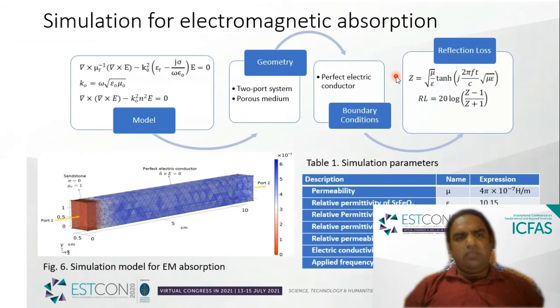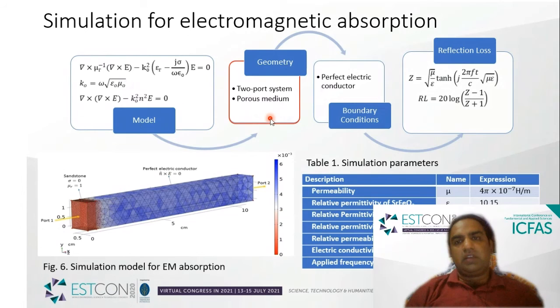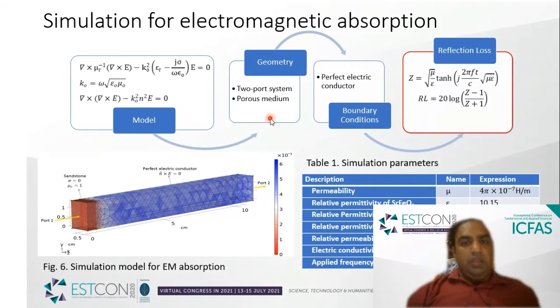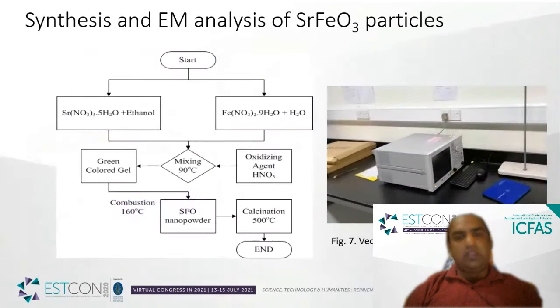So in the working part, we did some simulation for electromagnetic absorption, in which we proposed the model, and then we had some geometry in which a two-port porous system was used. We set the boundary conditions, which were the perfect electric conductor, and at the end we applied our model for the reflection loss. So this was the geometry in which on one side we placed the sample, and on the other side, when we applied the electromagnetic field on port one, we received the reflection coefficient or the transmission coefficient at port two. Then we calculated the absorption in that reservoir. Table one shows some parameters which were used in the simulations.